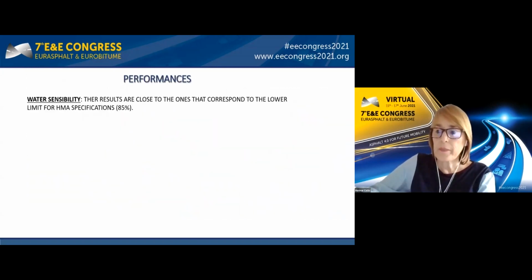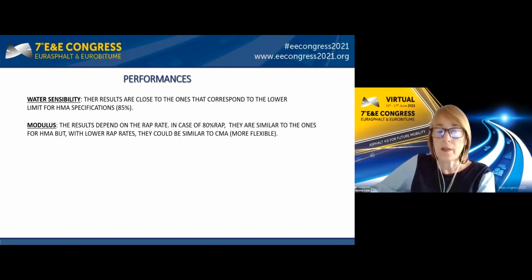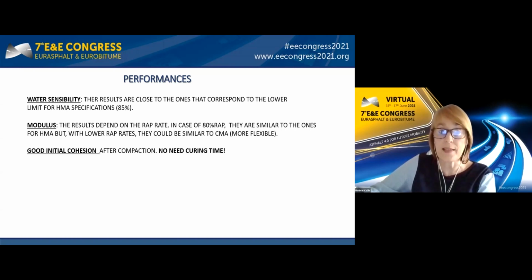As a summary, I would like to highlight 4 points. The first one is water sensitivity. The results are close to the minimum for the hot mix asphalt specification. The modulus: the result depends on the RAP rate. In case of 80% of RAP, it is very similar to hot mix asphalt, but with lower RAP rate, it could be similar to cold mix asphalt because they are more flexible mixes.